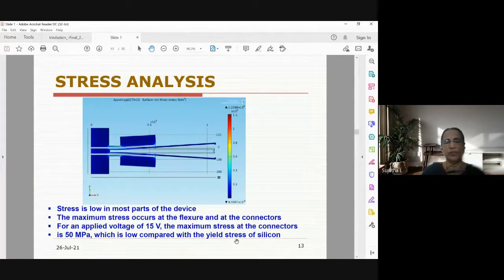When you compare to those values in gigapascals, here it is in megapascal, which is very, very low. So the structure will be rigid and will not break easily. For this stress, it will work fine. The maximum stress occurs at the flexure and at the connectors, and the stress is low in most of the other parts of the device. This is our observation, and it says that the structure is good. You can go ahead for fabrication. You apply the voltage of 15 volt, measure the stresses in the simulation, and based on that you can judge whether the structure will work fine after manufacturing.